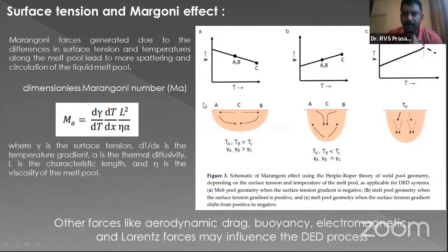Say, for example, if your surface tension gradient is negative, then you will have a melt pool which is wider, as shown in the figure. Similarly, the melt pool geometry will change when the surface tension gradient becomes positive. As shown in the next figure B, when it is positive, the melt pool shape and dynamics will change. And when it is initially positive and then becomes negative, the melt pool will be very turbulent and a different kind of pool is going to form. In direct energy deposition, a lot of other forces also play a role, like aerodynamic drag, buoyancy, and electromagnetic and Lorentz forces, which may also influence your melt pool dynamics. So that is with respect to the melt pool.